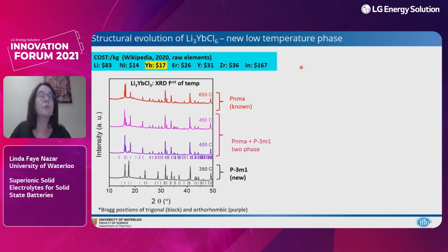So we've moved on to look at other materials. We've investigated ytterbium because obviously these materials are rather expensive. It turns out ytterbium is actually rather low cost compared even with zirconium and certainly compared with indium. And in this case, we were able to find a new trigonal phase of this material. It's new for ytterbium. It's not for erbium, but it is for the ytterbium phase.